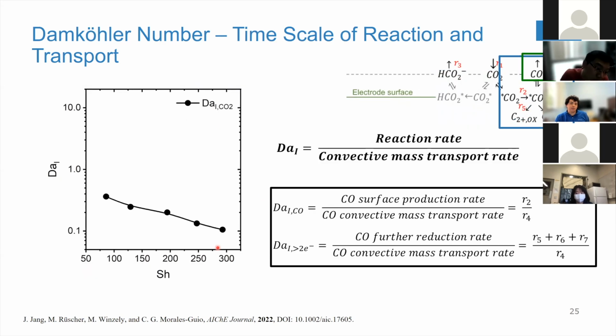And if we look at the further steps, what is key here is that this R4 process is a first order process. So if you change the concentration near the surface of the electrode for this carbon monoxide reaction, you should increase the flux. So what we do now is use this R4, this flux of CO that we know is a first order process, as an internal clock to estimate the reaction orders for the other processes. If this flux, which is first order, is affected in the same way as R7 or R6, then we can create those correlations and understand whether a process is really first order or second order with local concentration of species at the surface of the electrode.